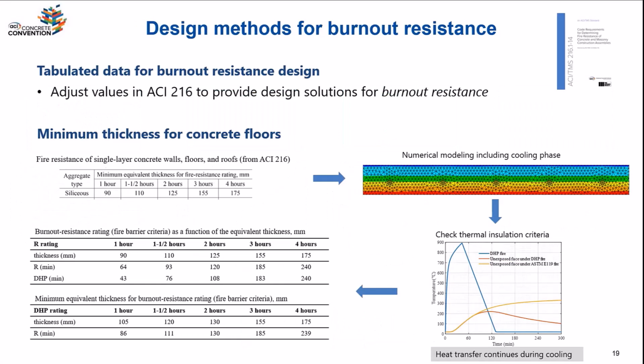So as the last part of the project, we looked at the current tabulated data in ACI 216, and we looked at what it would mean if we had to adjust those provisions for thickness, for cover, to make the members survive to full burnout, and not only for specific fire resistance time. So as an example here for the thermal insulation criteria of concrete floors, you have a table that gives minimum thickness in ACI for different duration of standard fire rating.